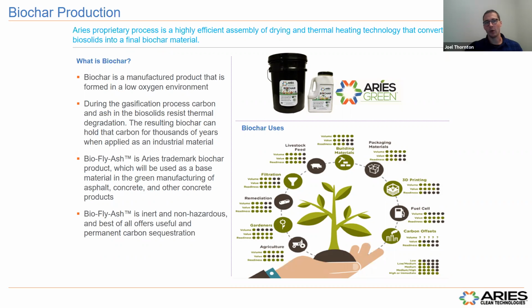And then that leads me to the fluidized bed gasification product, the biofly ash. This stuff has a much lower carbon content, about 5 to 10% carbon. The rest is ash. We've been working with the National University of Singapore, who have been doing tests on replacing fly ash with a mixture similar to this, with a small amount of carbon in it, and seeing good quality results in strength of concrete and the different concrete parameters. I'm no expert in concrete by any means, but they've shared some of those results with us.